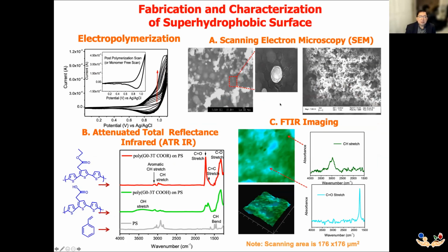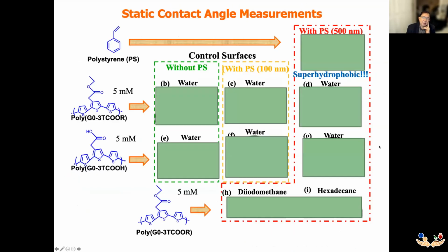Now, we serendipitously discovered that these are super hydrophobic films or materials when we overlay the deposition of another conducting polymer on top of these colloidal particles. By IR imaging, we can prove that we have both the polystyrene latex particle, which was the original material, and the polythiophene that was added on this material by potentiostatic and cyclic voltammetry methods. So the result is this roughness actually affects the wetting behavior.